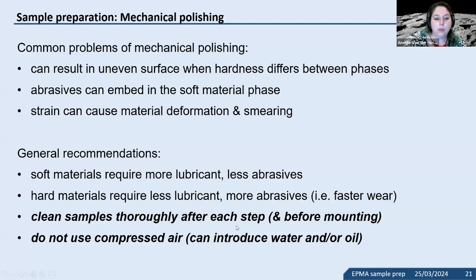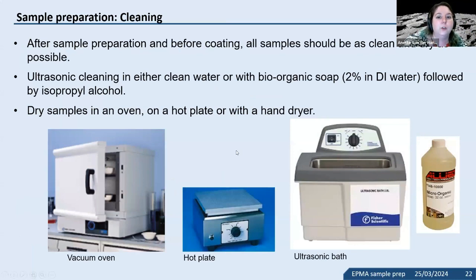And for each cleaning step and at the end, you do not usually want to use compressed air that you can get just through a normal line. There are special handles or endpoints for that can have a filter that can make it useful. But yeah, usually the compressed air, if it's just the building line, can introduce water and oil. And so it's not a final clean surface anymore. Different ways then when you're done, usually you want to clean with some alcohol.